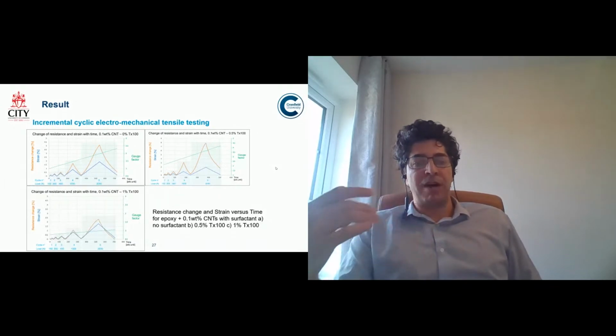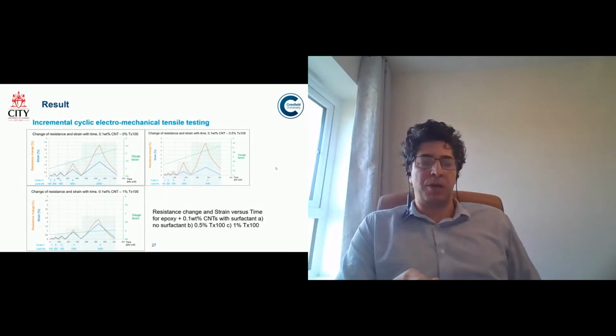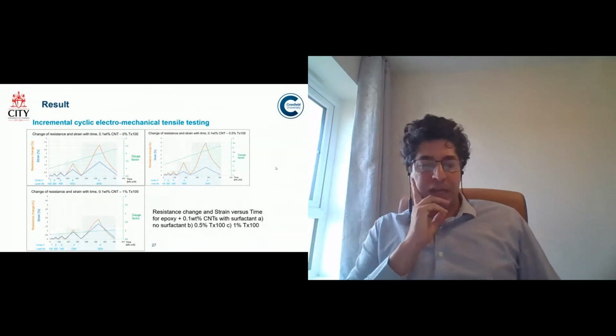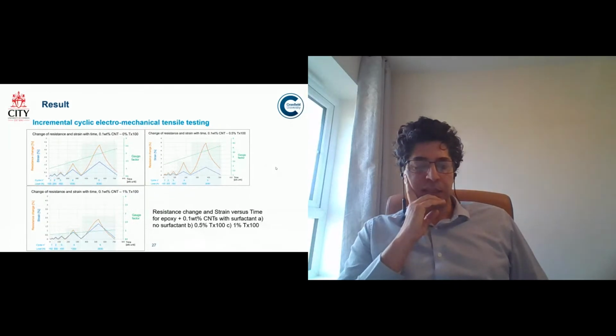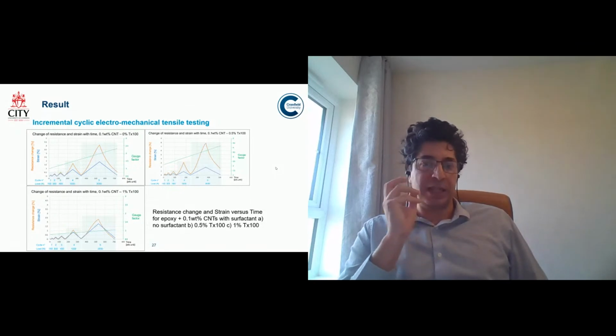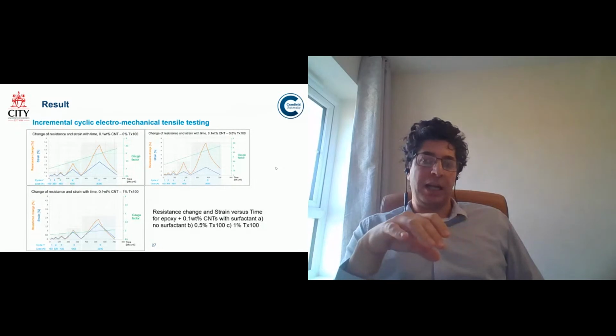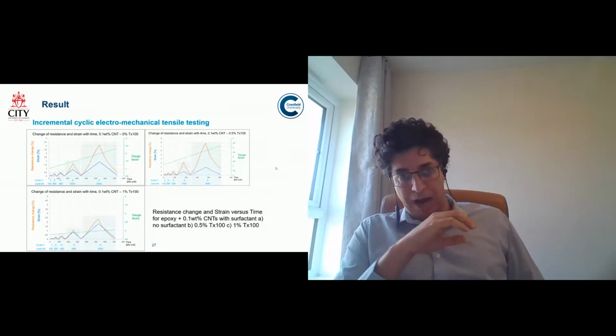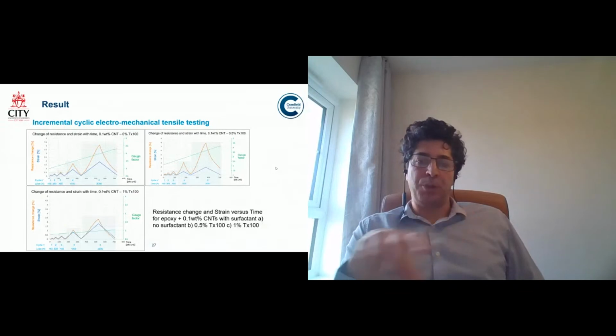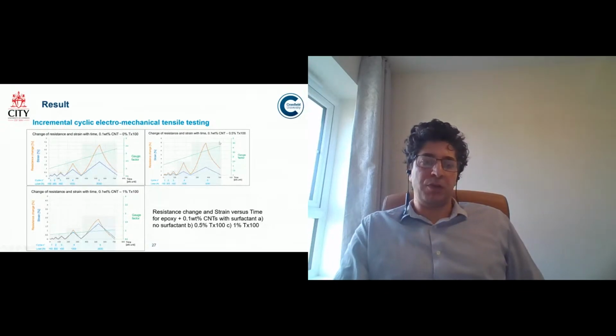So we came up with a mimic of varying operating conditions in a very controlled laboratory scale. But we ended up with a very interesting result. This is in the Scientific Reports paper on the composite assembly adhesion bonding as well. So we did this strategy with cyclically increasingly varying load. Just imagine that if you focus on the dark blue line, there are loads and the cycles of these loads changing in terms of the strain at the loads. The loads have been incrementally increased, 150, 300, 450, 1,000.